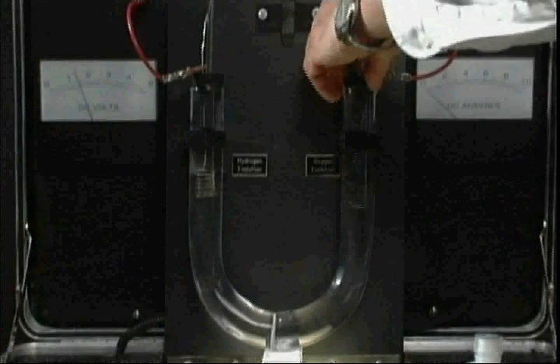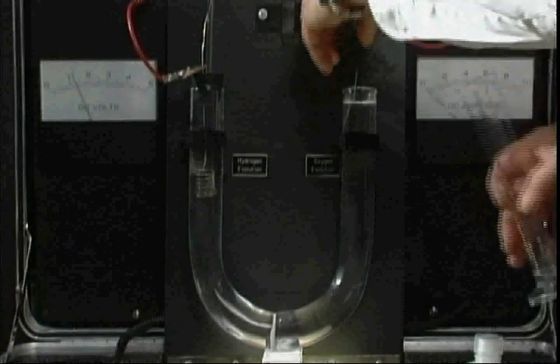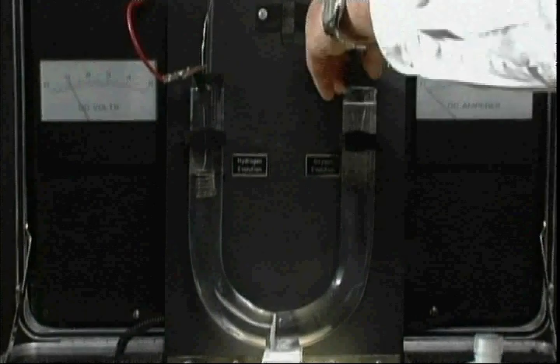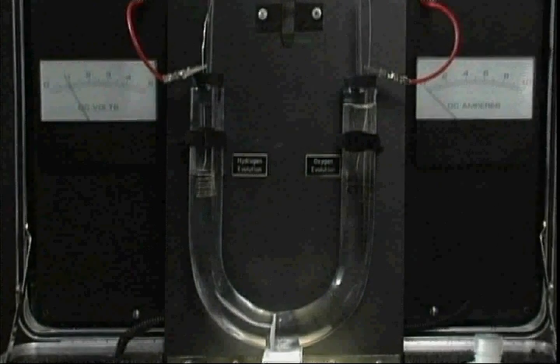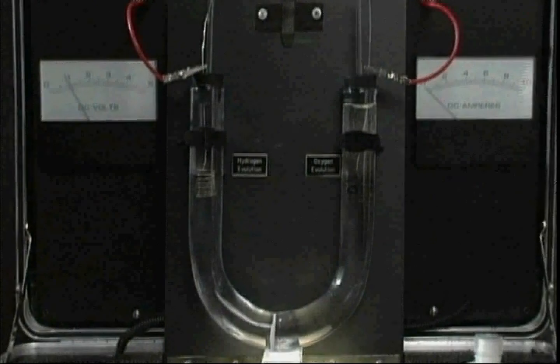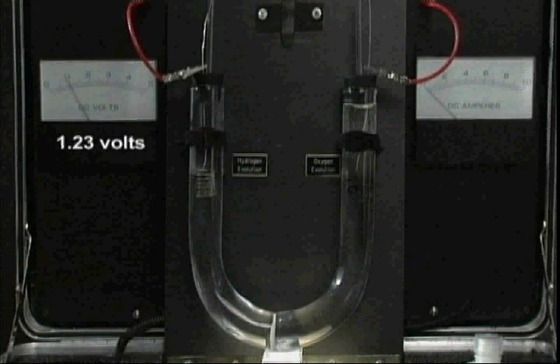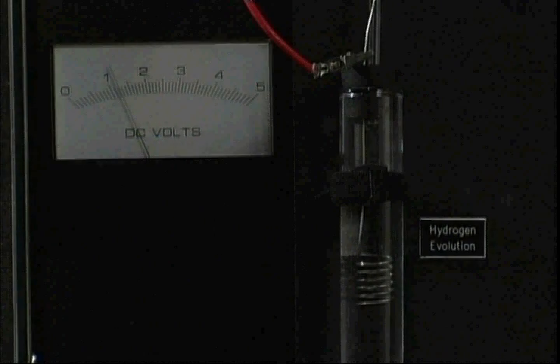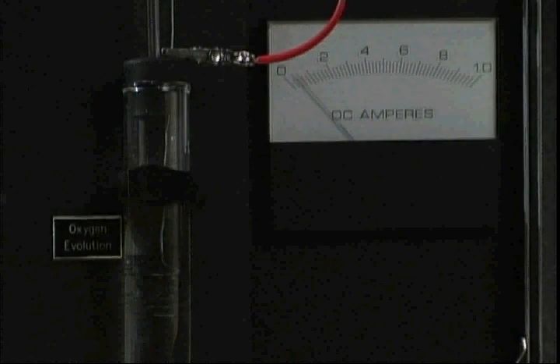Next, I will begin by adding deionized water to both compartments. Theoretically, hydrogen and oxygen should be evolved at a voltage of 1.23 volts. However, nothing happens at these voltages because pure water is a very poor conductor. Even at 3 volts, gas evolution is not observable.